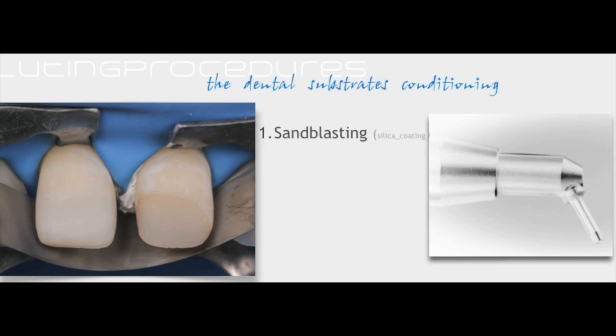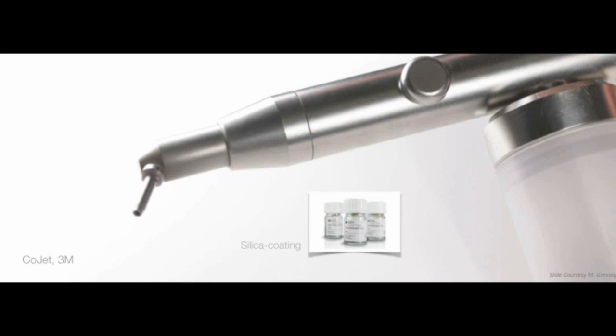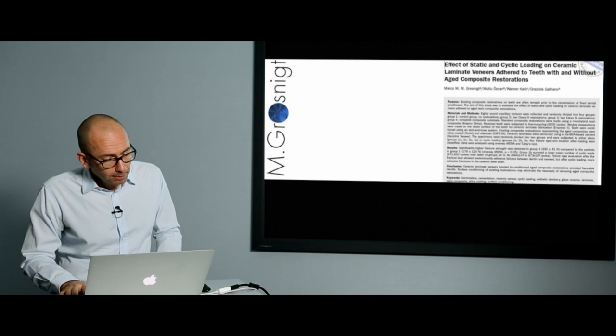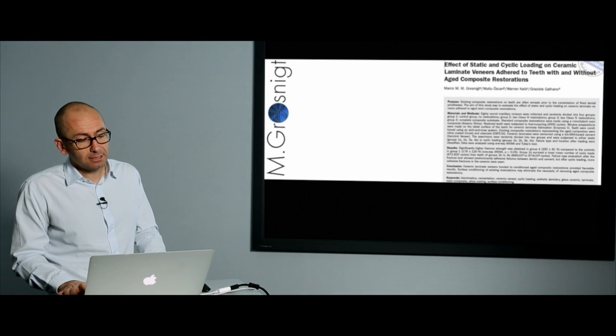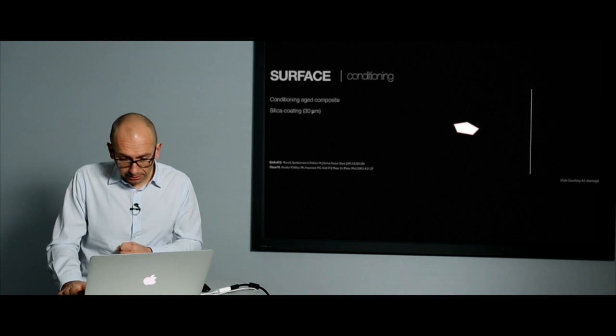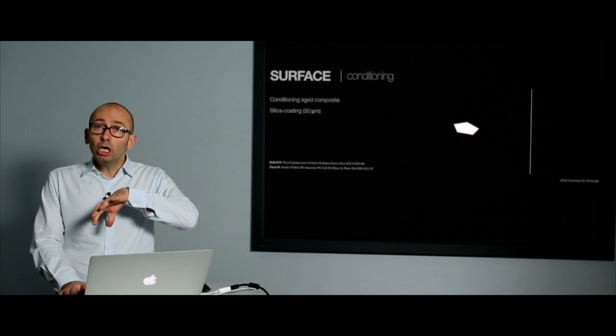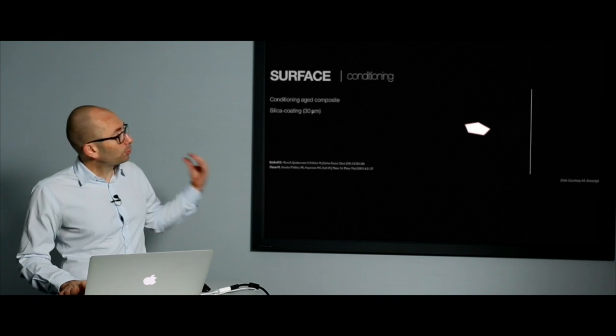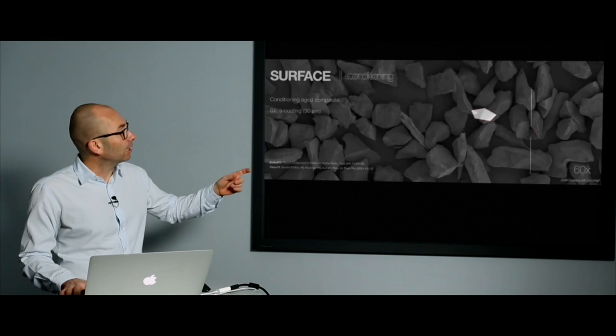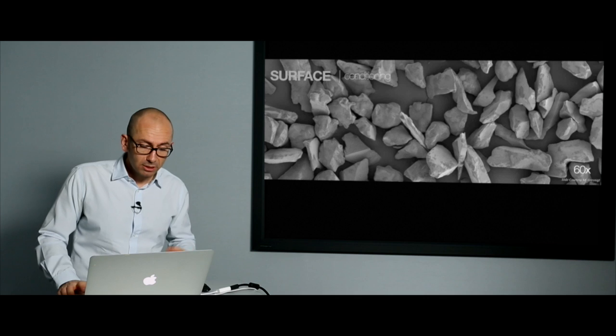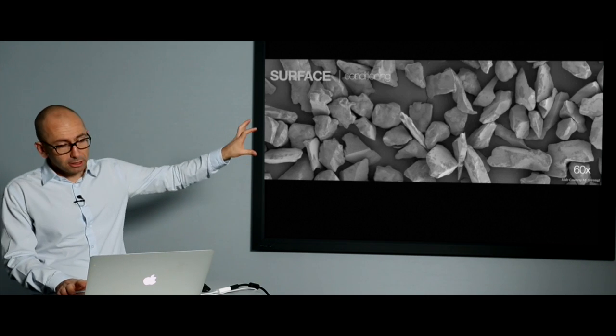And I'm using for the purpose the CoJet from 3M device, which is a very easy sandblaster to use with a special sand, which is the silica coating sand. Because in that case, you won't only clean and roughen your surface, but you will also create a silica coating, which is a way to promote the adhesion a bit more. We've got a very good paper of Marco on the subject, and this is what it is about. This special sand is alumina grains coated with silica. Once you throw the grains on the surface, the silica will stay on the surface and the alumina will go out. This is how those grains look.